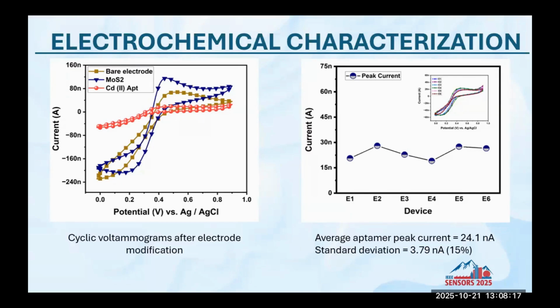Now, we have been saying that we have been able to eliminate leaching and get a uniform current level, as it was not very convenient to get in the case of GCE due to the drop casting variability. For that, we have taken the current at the aptamer functionalization level for 6 different electrodes, and we see a variation of only 15%, that is around 4 nanoamperes of current. So we are able to get a uniform current level after the aptamer modification.